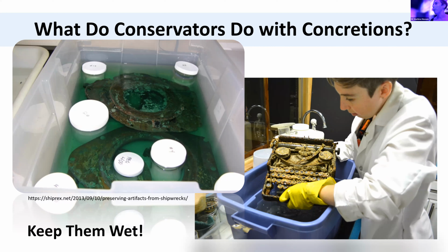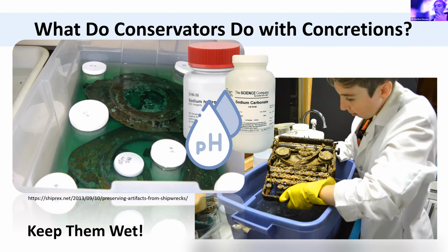You can imagine where that might be a problem, where all of a sudden you have the salt growth happening inside your artifact. Or you have something made of metal that has kind of reached a point of stability in its water environment. You're suddenly bringing it to a new environment where it's being bombarded by oxygen, and all of a sudden the salt is coming out of solution. So you have all these electrolytes. So not only do you have a challenge from the crystalline growth and things dehydrating and falling apart, you also have renewed corrosion happening as a result.